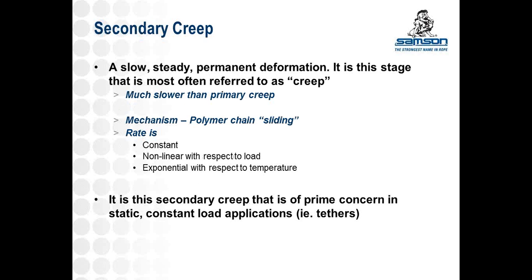Now that slow zone is this secondary creep. This is really where those polymer chains, which are already standing in rows next to each other, nicely in line, begin to slide past their neighbors. And this rate is, assuming that the temperature and the load are the same, going to be constant over time. And like I said, it's going to be anywhere from 10, 100, 1,000 times slower than that first initial bit. This secondary creep is really mainly of a concern to applications where there's a long-term steady load, or there is a high temperature, or a combination of both.